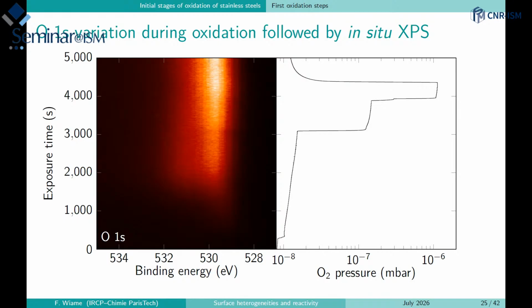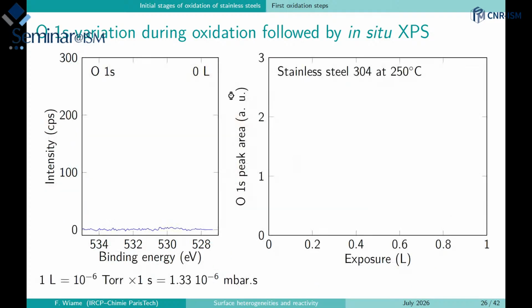So you have the pressure as a function of the time on the same scale. You can see that for very low pressure, we already have some oxidation. If we increase the pressure, we can speed up the oxidation of the surface. In fact, I can show you how it looks. So here we are measuring the oxygen 1s as a function of the pressure, and here you have the exposure in Langmuir.